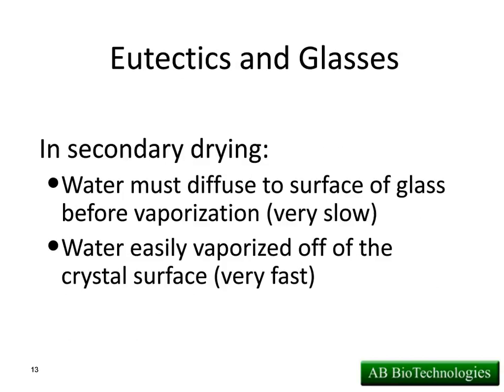Okay, we talked about that. So in secondary drying, in an amorphous phase, water's got to diffuse to the surface of the glass before it can vaporize. So this can be a very slow process. And if you go too quickly, you can actually collapse your product on your ramp up to secondary drying. Well, that's not the case with a crystalline formulation. You can be very aggressive. And in some cases, as I said, we've been able to do primary drying and skip secondary drying altogether with a crystalline phase.